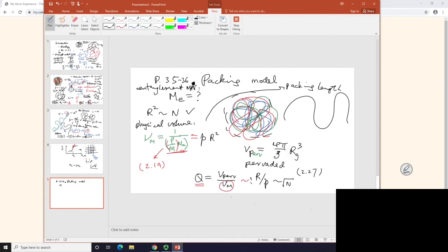So that's coming from high molecular weight to low. I'm here telling you from low to high. In between, you meet that point. That is, there will be a point where it is sufficiently clouded. And that's when you start to have entanglement, beyond which you should start to think about chains confined in a tube. Get the concept? So as I keep increasing my molecular weight, there will be one point where it seems reasonable to think my black chain is in a tube.